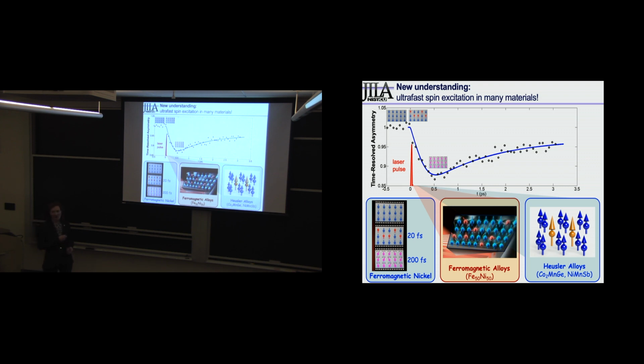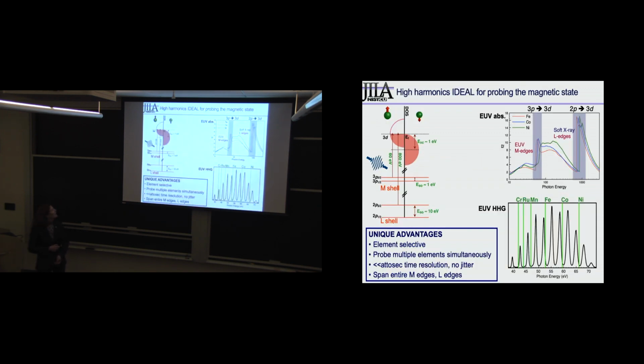Okay, so let me try to explain to the best of my understanding. There is no theory on this right now, but this is what we think is happening: you have very hot electrons, they have enough energy to flip a spin. When you do that, you conserve angular momentum because it's a high energy magnon, so you have made the spin flip, but you haven't dissipated the angular momentum. But the interesting thing is that this happens during the laser pulse, and once that's made, the material will undergo a phase transition. So you've launched the magnetic phase transition. So it's not that different, but it's just interesting.